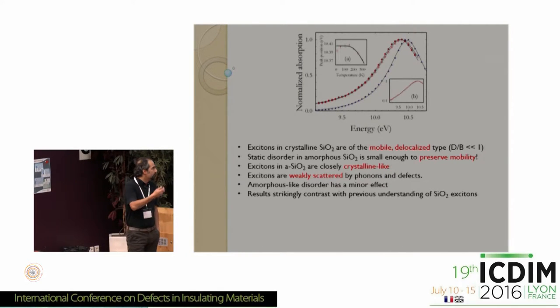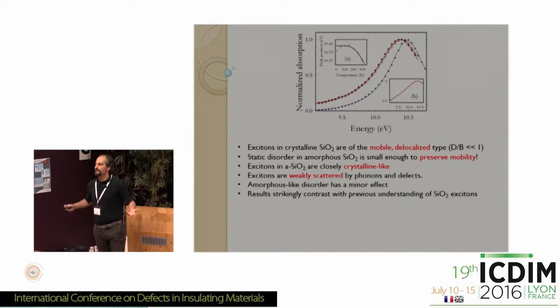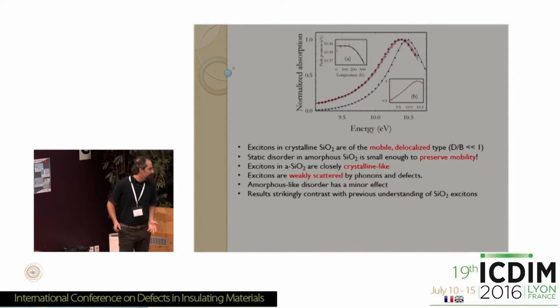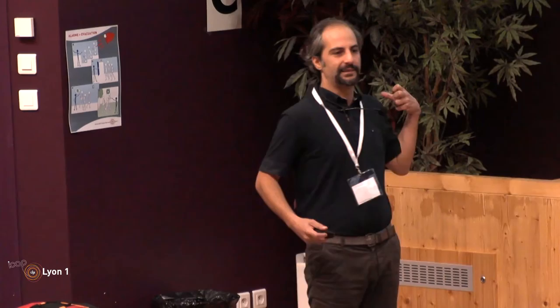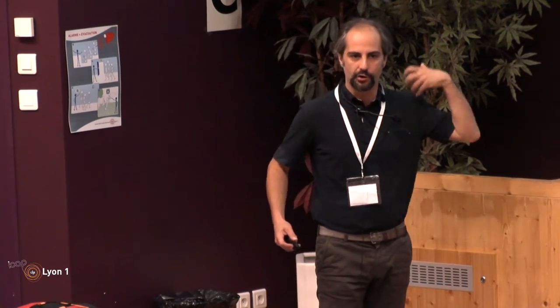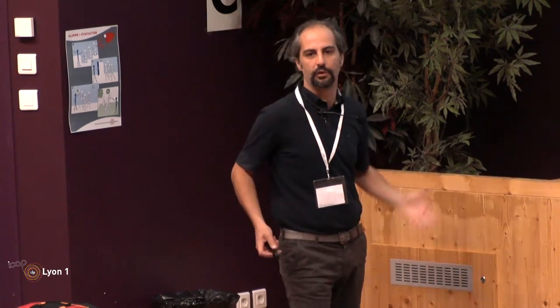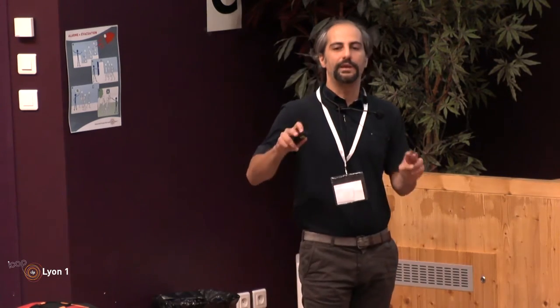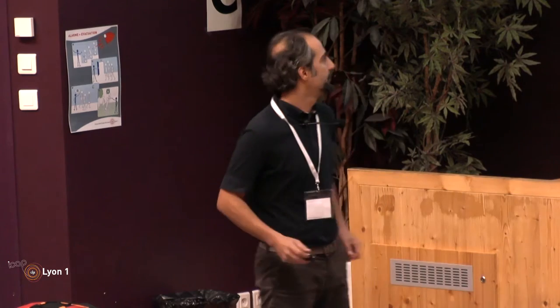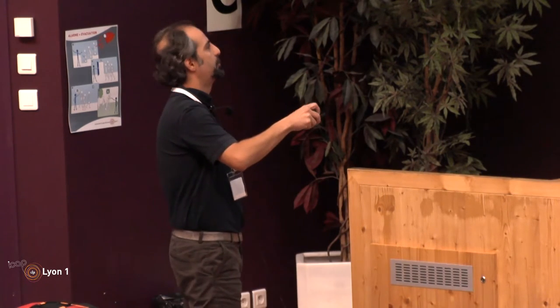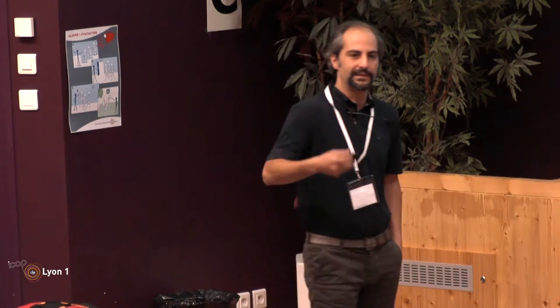Now, this is interesting because if you think of it, an amorphous system like silica may be expected not to be capable of supporting exciton mobility because of disorder. The first thing you would think to be lost in a disordered system is the ability to transport energy or charge or whatever needs to be transported. Well, this work proved that this is not the case for excitons. So excitons in amorphous silica are closely crystalline-like and capable of strong mobility. Okay, which contrasts with the previous understanding of excitons in SiO2.